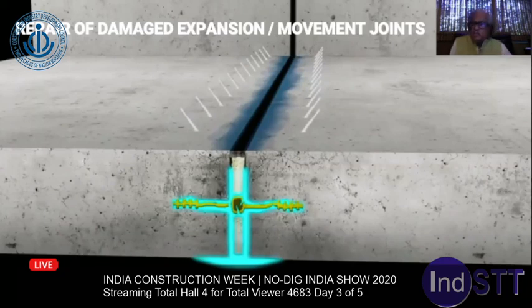Some physical barrier you should put. If they have not put a physical barrier, and if your width is 60 centimeters, you can put some Silodex board up to say 30 centimeters. So automatically you get a physical barrier. Go behind that 30 centimeters at a 45 degree angle. Inject a gel inside it. A little bit of gel will come because there is not a sealing with the thermocol or Silodex board or dimple boards. Some material will go there. It is good for you.